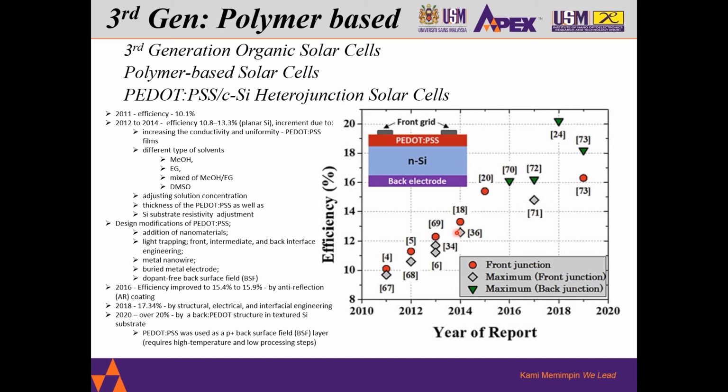The efficiency was improved up to 15.4% by introducing the AR coating without additional light management such as texturing or a pillar system.